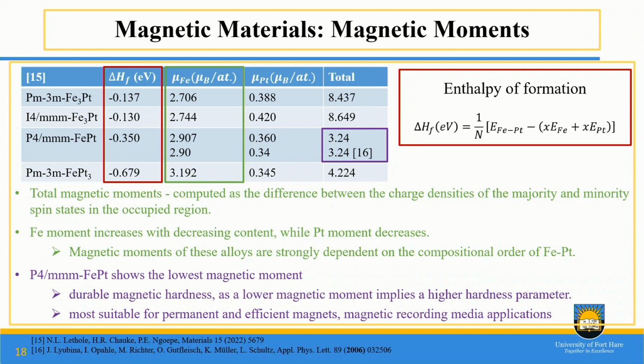And then we find that this equiatomic one also has the least magnetic moment. So this is going to lead to durable magnetic hardness, as a lower magnetic moment implies a higher hardness parameter. So this can make it very suitable and also efficient for permanent magnets.